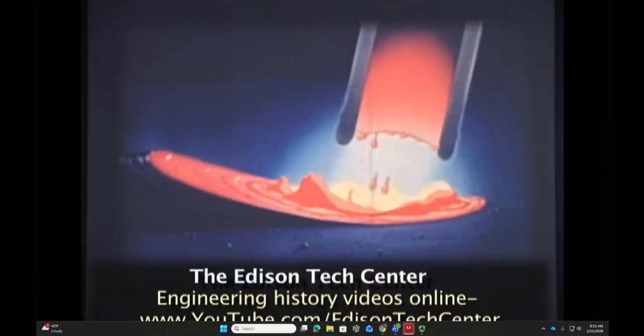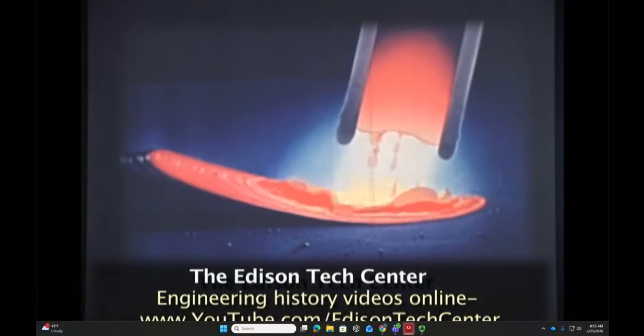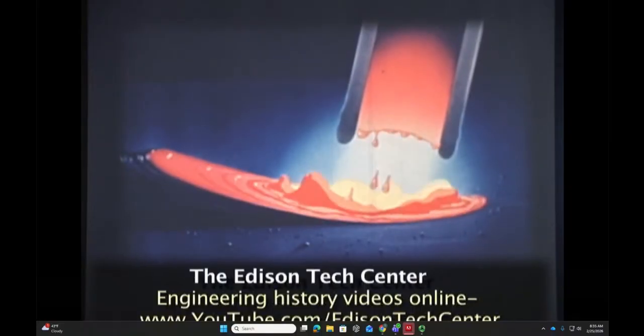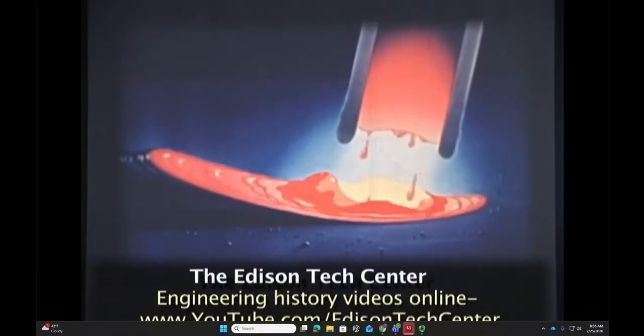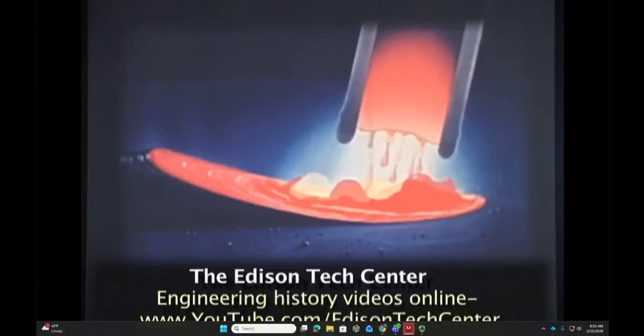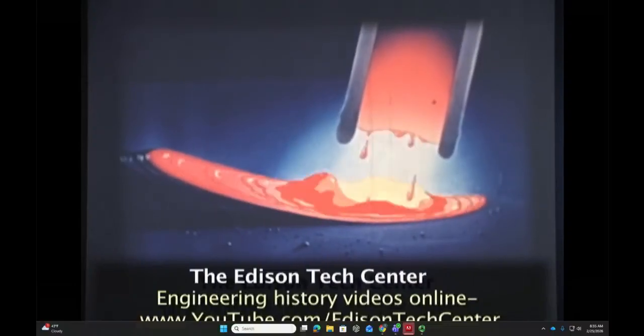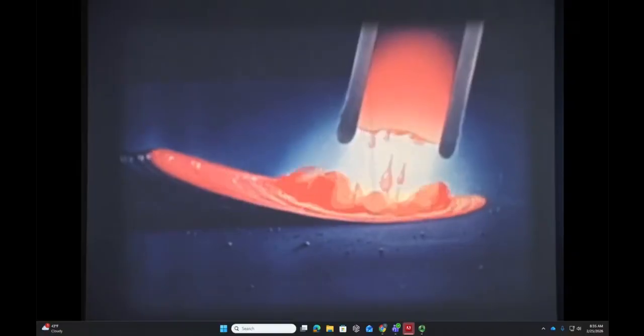The movement of this metal toward the rear of the crater and the depth of the crater are an excellent check on the quality of the work. The operator should learn to use it as his guide. At the same time that the metal is melting, the coating on the electrode is being consumed. This takes place slower than the melting of the electrode, which shields the arc and helps direct the flow of metal. It also permits the use of higher currents, with the resultant faster deposit of weld metal.